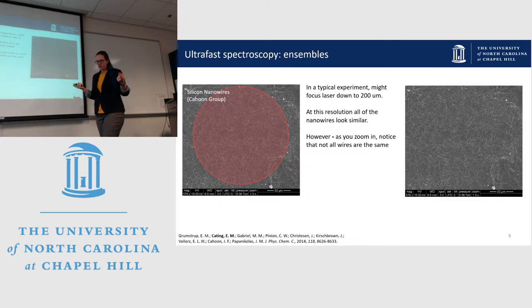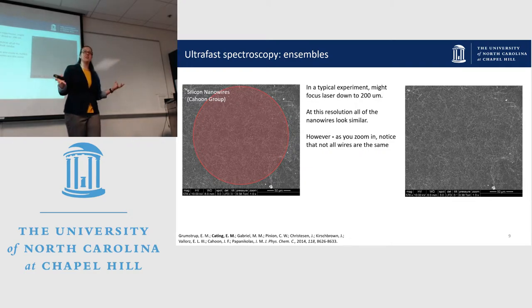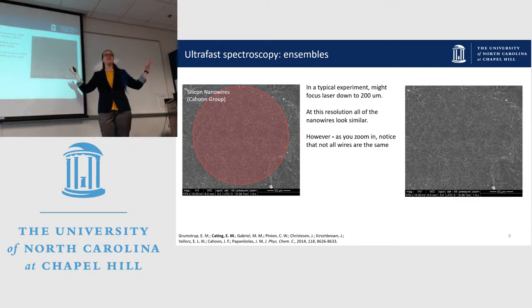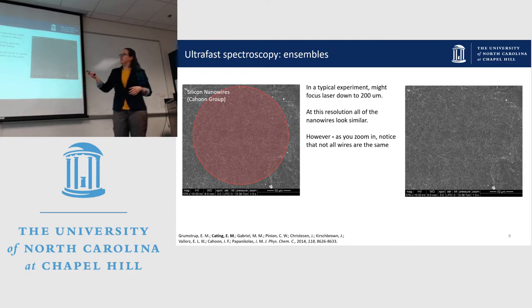So one way that you might think of to do this, and the first way that we did try to do this, was by looking at many wires all at once, right? So if you have a typical pump probe experiment that's not in a microscopy mode, you might focus your spot size down to about 200 microns. And at this resolution, you're covering thousands of nanowires at once. And they all look like they're kind of the same, right? So maybe this makes sense. Maybe all the wires that are grown at the same time have the same quality surface, and you can just get one lifetime.